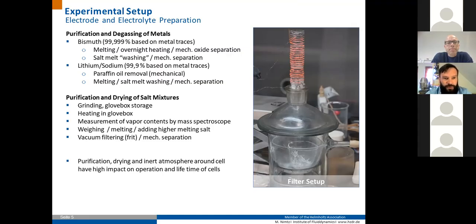It's also possible to use a molten salt to wash the oxide from the liquid metal, and also to use mechanical separation, basically by scratching off the impurities of the solidified metals. Same procedure is for lithium.